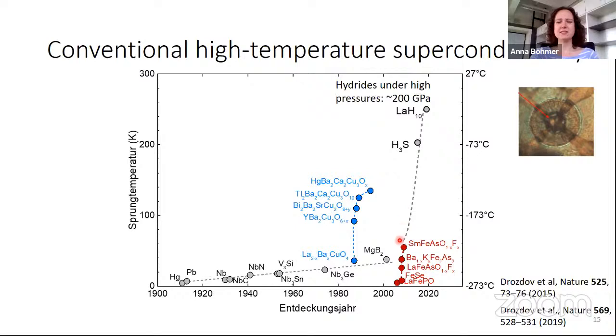So now I have to change my scale on my history plot. And that was only a few years back. Superconductivity was found at, well, almost room temperature. It's not quite room temperature, but this is outside temperature in winter in Siberia, for example. The drawback is this is superconducting at only 200 gigapascal of pressure, so that's very far from atmosphere. So applications are still far, but fundamentally we have found a really high temperature superconductor here and these hydride materials.